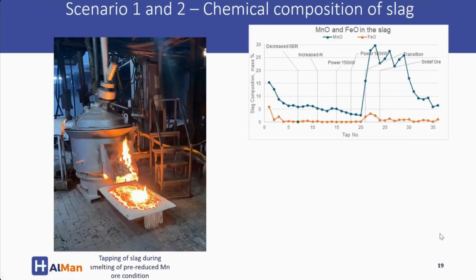Now in terms of the slags, as you can see, this is the MnO - we progressively had to increase the aluminium so that we can reach that target below 4% MnO. When we transitioned to the pre-reduced ore, you can see the manganese, because of the high manganese oxide in the pre-reduced ore, the residual manganese oxide in the slag was quite high. That's why we had to significantly increase the aluminum addition so that we can drop it significantly to the target MnO in the slag.